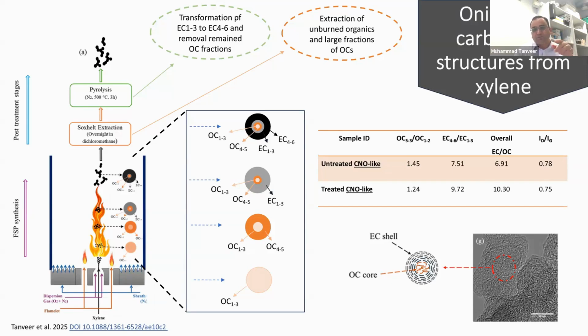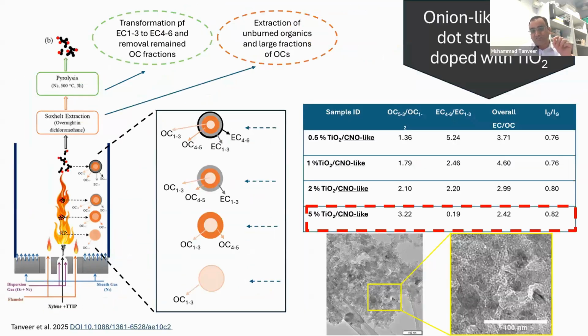And also we have doped these carbon nanostructures with titania. So we have observed that if we dope titania in the carbon nanostructures, then the particles are more defect induced, and their morphology is also quite defect oriented compared to the graphitic one.